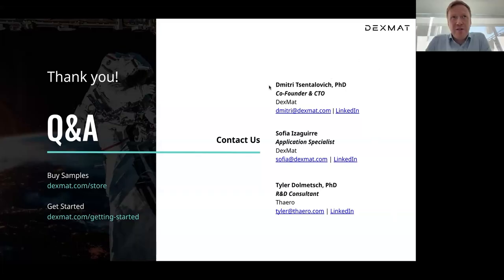Yes, I can give you a bit of a flavor of the testing that we've done. We actually have some testing ongoing with the Mississippi Polymer Institute, where they're doing accelerated aging tests by studying the effects of different humidity and temperature conditions on Galvorn. We do know that Galvorn has been shelf stable for over 10 years from the initial Galvorn materials that were being produced back in about 2015, and they have not had any degradation in conductivity or strength. However, we have not done a lot of UV exposure experiments, and that's one of the things that is going to be evaluated with some of this accelerated aging testing that we're doing.